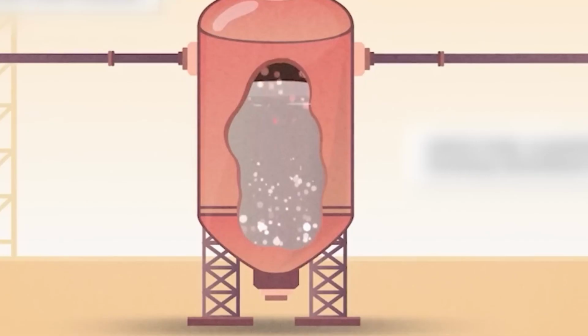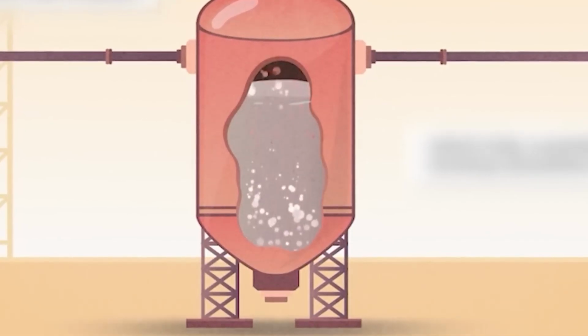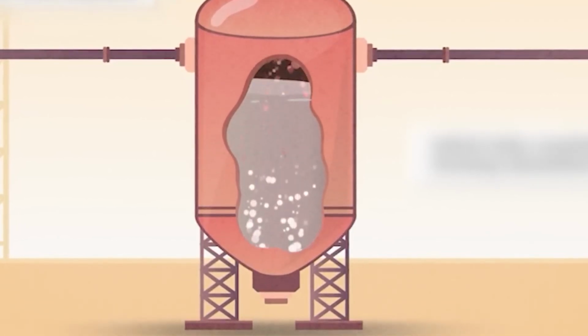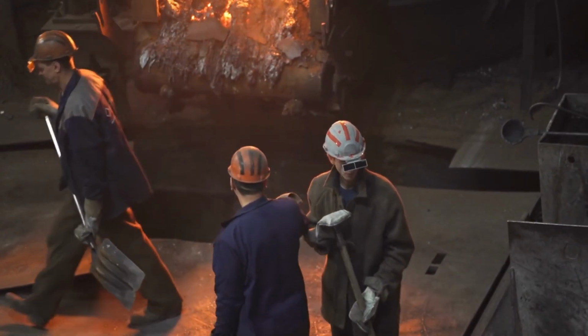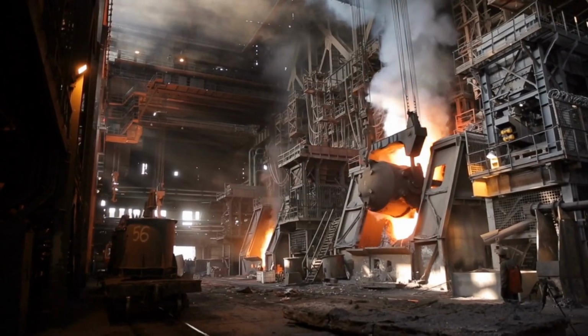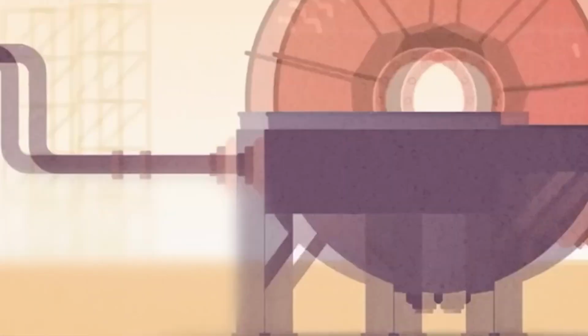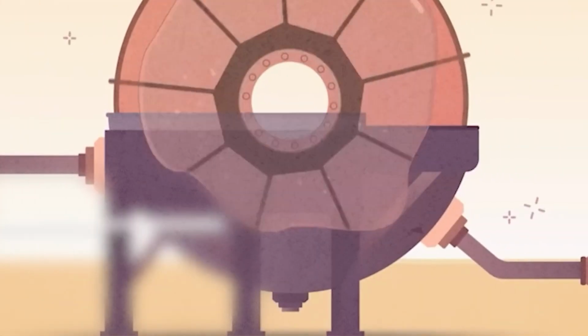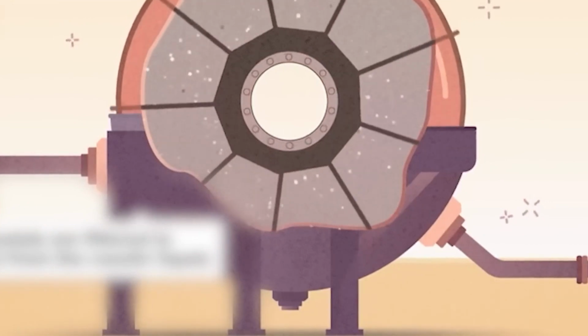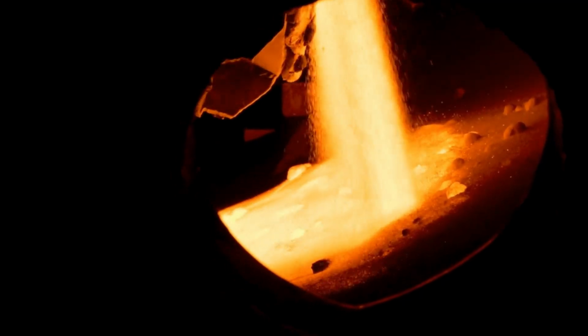As they descend through the liquid, the dissolved alumina begins to attach to them, causing the seed crystals to grow in size. As alumina attaches to the seed crystals, they gradually grow and eventually precipitate out of the solution. Once removed, the crystals go through a washing process before being transferred to a kiln for calcining, a high-temperature treatment that removes the chemically bonded water molecules from the alumina.